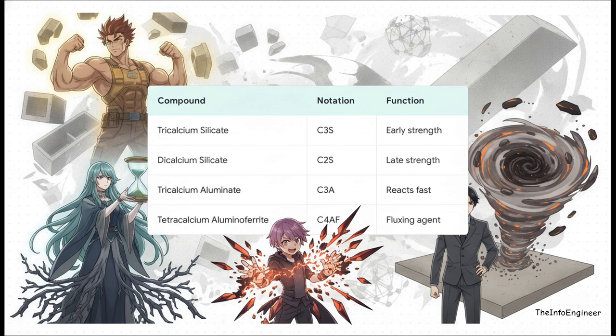Simply put, C3S is the powerhouse that gives your concrete its early structural strength during that critical first week. C2S, on the other hand, is the late driver. It reacts much more slowly to build long-term durability over months and years. C3A is the highly reactive one that wants to flash set, and C4AF acts as a fluxing agent and gives cement that classic gray color we all recognize.